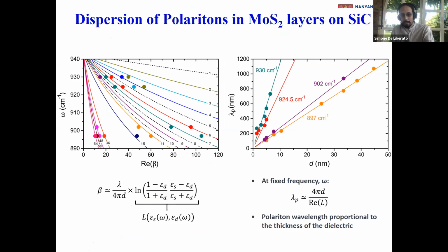Yes, I see this happens for extremely small layer thicknesses. I would like to point out that we have seen that when you reach those kinds of dimensions, non-local effects start to be important. We have seen how non-local effects, with the coupling, with the actual propagation of phonon modes, start to affect the results of nanolayers around a few nanometers. There is a PRX from a couple of months ago in which you can find it. So this could actually provide an explanation of why those results deviate from the local theory at small thicknesses.